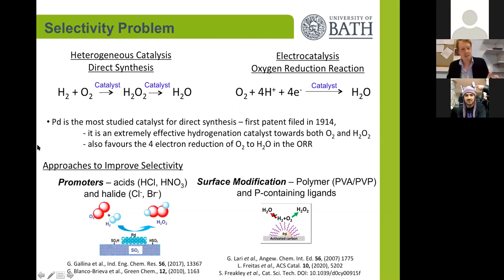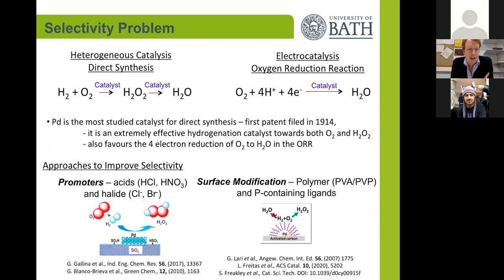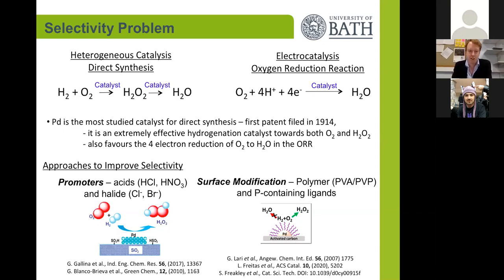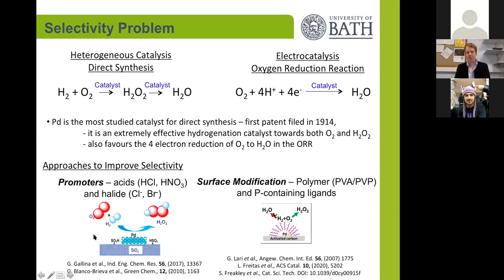Many approaches have been taken to try and improve the selectivity of pure palladium catalysts. In the heterogeneous systems, this mainly focuses on adding promoters to the reaction solutions such as mineral acids like nitric acid or HCl. This stabilizes the synthesized hydrogen peroxide. Also, the addition of halides to selectively poison some of the palladium particles results in an increase in selectivity.